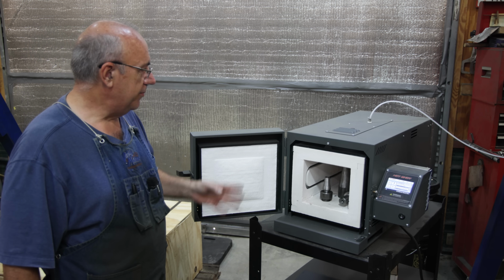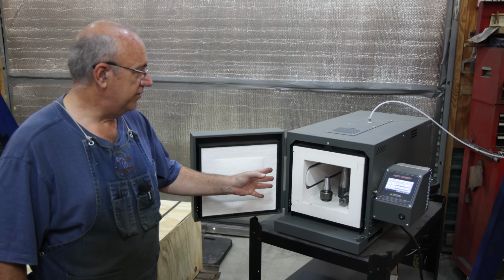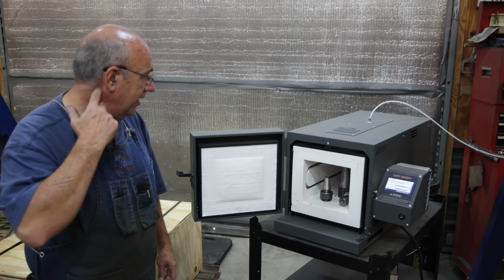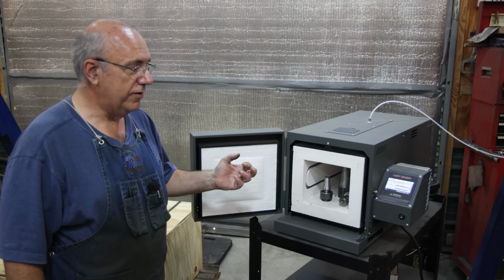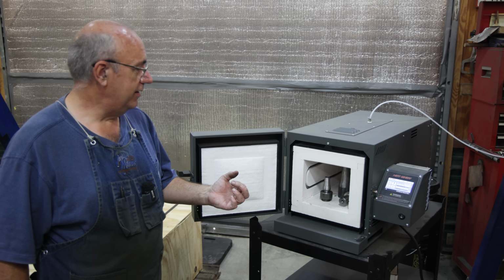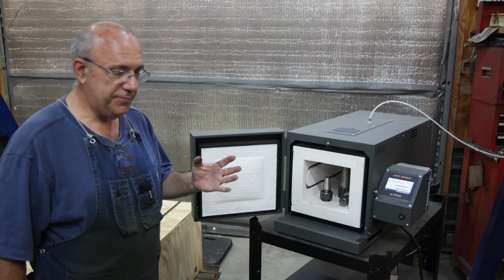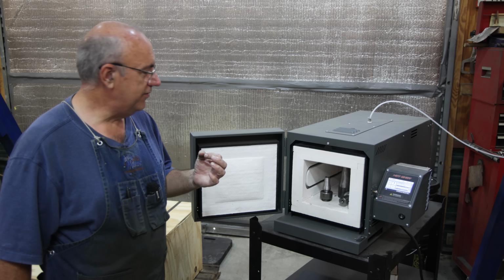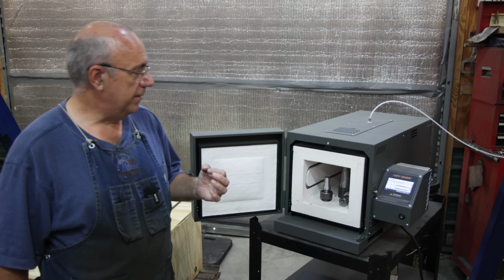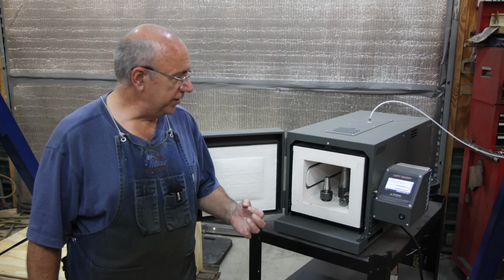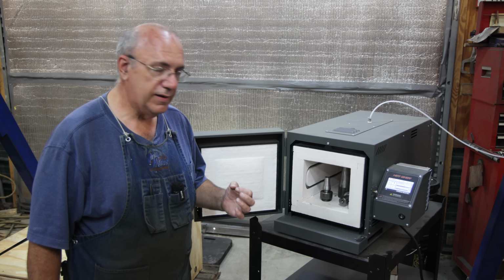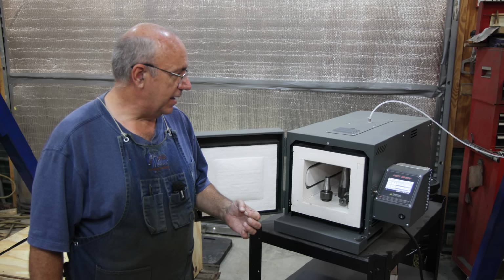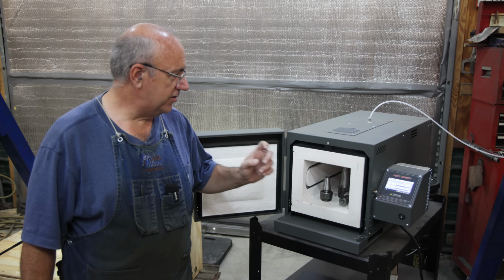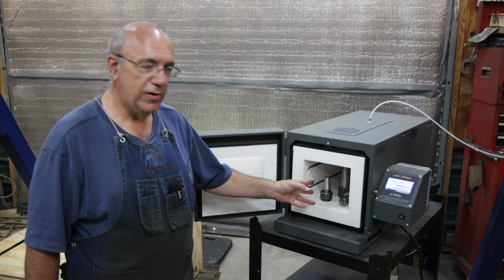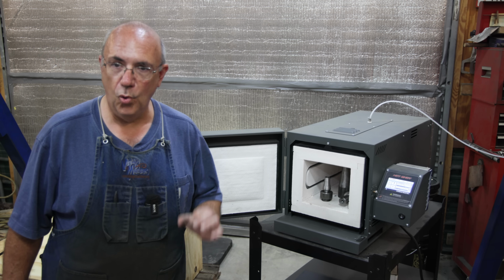A couple of things to note. I'm using a hot shot oven here. This is my heat treat oven that I use. I've got it programmed for 4140, which is basically the heat treat is we're going to ramp it up to 1575 degrees Fahrenheit. Once it gets to that temperature, we're going to hold it there for an hour and a half. At that point in time, it'll give me an alarm to tell me that I'm there. We'll come over here, we're going to pull these out. We will quench them in oil.